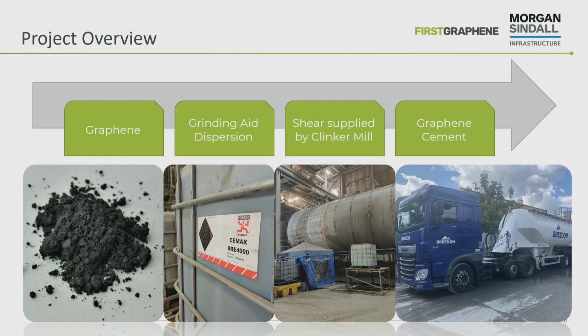So we need to target that point, get the graphene into that grinding aid, disperse it well, and immediately dose it into the mills. So you can see here on that middle right image, that's one of the mills at Breedon Cement Plant, and that was our little gazebo there where we did our dispersion process. And I'll show you inside the gazebo, there's nothing secret there. So we added that grinding aid, we dispersed it, dosed it straight onto the belt, it went into the mill, and then from that point on, it was just like a regular cement.